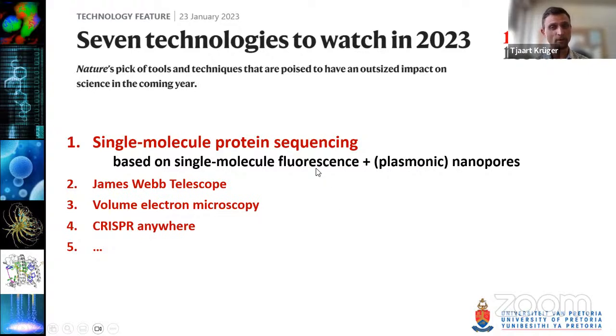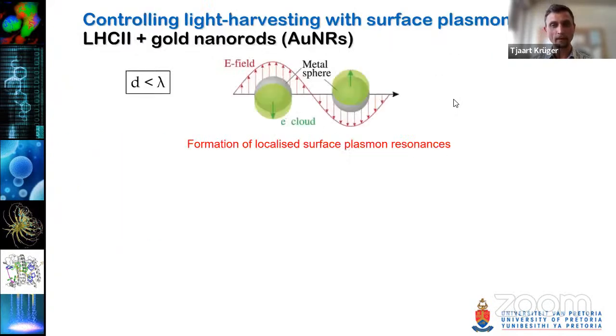And yes, we are working on single molecule fluorescence techniques, and we have also worked on plasmonic systems. Now I would also show you a combination between these two: integrating LHC2 with gold nanorods in order to control some of the photophysical parameters. If the dimensions of a metallic particle are smaller than the wavelength of the incident light, then the incident electric field is going to lead to a coherent oscillation of the conduction electrons on the surface of the metal. That will form so-called localized surface plasmon resonances, which have a lot of interesting applications.